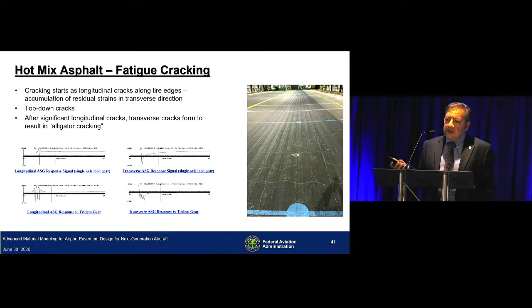And another thing is, whenever there is a crack formed, you want to know whether this crack is surface initiated or is coming from the bottom, because most of the design procedures assume bottom-up cracking in the asphalt. In my 28 years at this facility, I have never seen a bottom-up crack. All the cracks have been top-down. And I remember a presentation given by Professor Andre Molenaar from Delft University in one of the ISAP conferences, where the title of his presentation was Bottom-Up Cracking, a Myth. And I'm one of those people who have never seen it. And we have built even thinner sections with 3-inch thick asphalt pavements, and still it's been top-down.